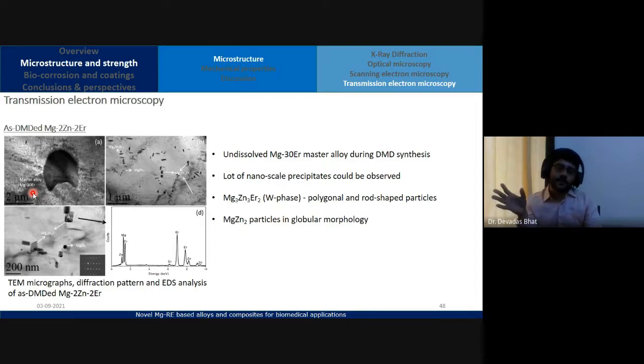When it comes to erbium and many other rare earth materials, they're very expensive. Okay, they are hardly used in the purest form. So they are available in what is called a master alloy. So you have an alloy which has a major amount of magnesium, and 30% of erbium. So when we add this master alloy into my composition, I change my pure magnesium component, since there's already magnesium here in the master alloy. So I designed my addition of different weights of raw materials such that I get my desired final composition.